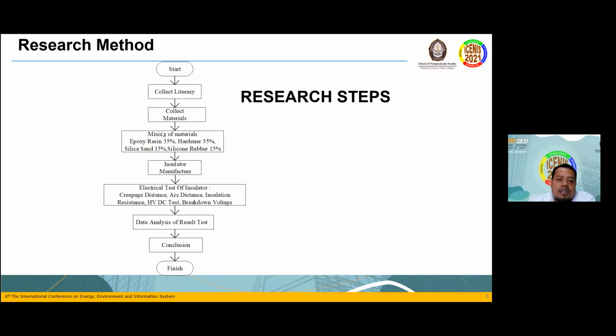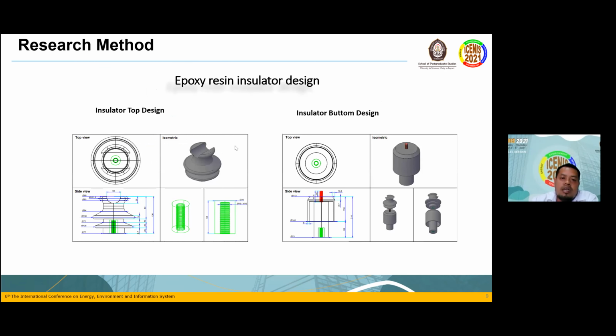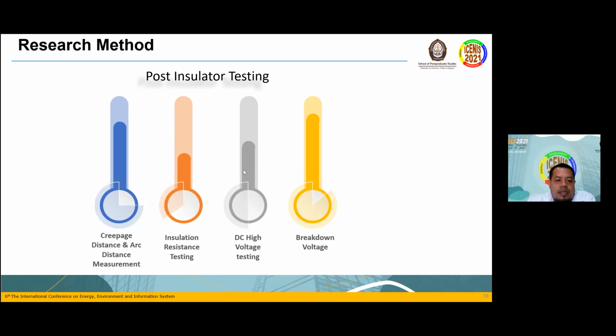Research steps. Mix of the material: epoxy resin 35%, hardener 35%, silica sand 15%, silicon rubber 15%. Then electrical tests of the insulator: creepage distance, arc distance, insulation resistance, high voltage DC test, and breakdown voltage. Epoxy resin insulator design: insulator top design and insulator bottom design. Testing covers creepage distance, arc distance, insulation resistance testing, DC high voltage testing, and breakdown voltage.